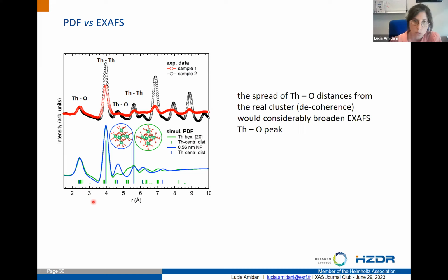And I want to mention, this is just my opinion, that the fact that you see here the first peak, which is the thorium-oxygen distance, is spreading over a series of distances, is quite relevant to bring the coherence probably in the XANES signal, which has a much higher sensitivity, I think, at least for those measurements.